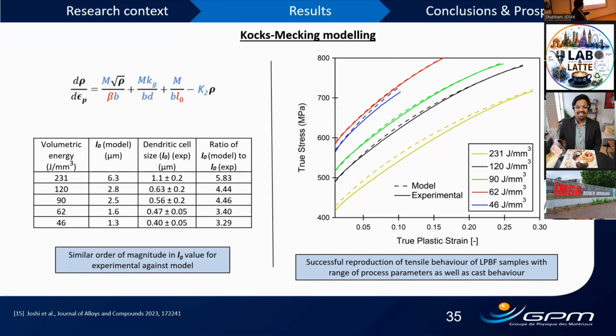What we proposed here is a correction factor depending upon the overshoot that this model gives. So using that correction factor, which was 0.22 actually, you can directly use L0 from experiments. So you do not even need to model-optimize this value. Just beta needs to be optimized and the model works.